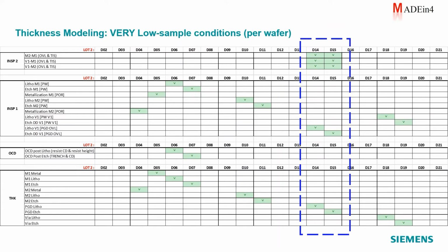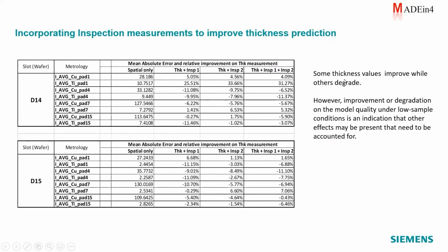Something that, again, illustrates this problem of very low sample conditions. We want to generate a model for these 2 individual wafers that is going to explain what the thickness is, and we are going to consider what happens when we add information from inspection tools. What we can already start seeing here is that while some thickness values improve and others degrade, the improvement or the degradation in the model quality under these low conditions is an indicator that other effects are present.